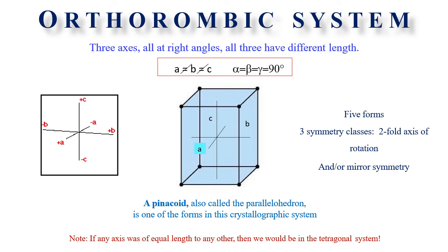Now we know that there are certain specimens which do not follow the rule of macro and brachyaxis. So we rather say that we have 3 axes of unequal lengths. In this crystal system, we have a is to b is to c equals 0.6290 is to 1 is to 1.3123.